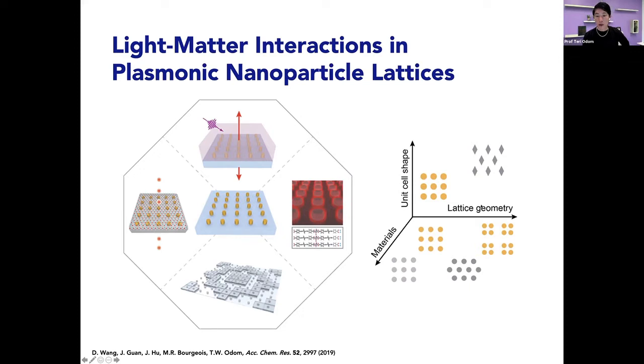So if we just take a slice of this phase space, we can control the unit cell shape. These can be cylindrical or diamond-like shape, triangular-like shape. There's a range of different shapes that you can tune, and this controls the localized surface plasmon properties. We're able then to also control the lattice geometry, so they can be simple in terms of square lattices, or hexagonal lattices, Kagome lattices, honeycomb lattices, even superlattices or arrays of arrays. And then we also have the ability to tune along a different axis the materials. So there's a very broad space that we can operate in, from the UV all the way to the mid-infrared.